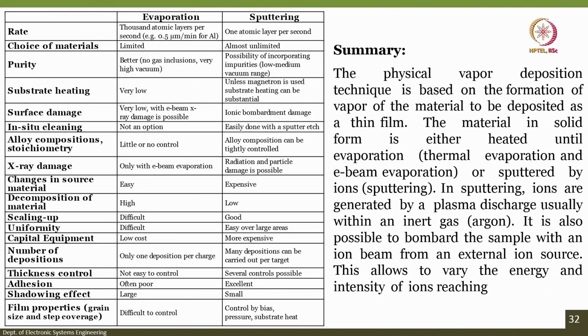The shadowing effect is large, while in the case of sputtering it is small, but if you compare CVD to this PVD, then the shadowing effect is also comparatively poor and the uniformity is larger. The step coverage is better in CVD compared to PVD, but the step coverage of this sputtering system is better than the evaporation system. Finally, when it comes to film properties like grain size and step coverage, which are difficult to control, we can control them by bias pressure and substrate heat in case of sputtering.